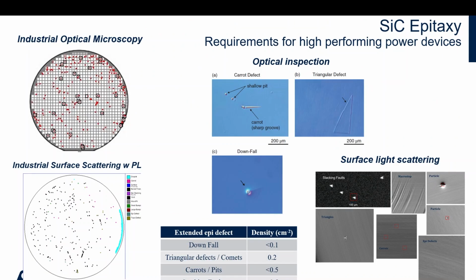And of course, you have to inspect defects. Each defect of silicon carbide after epi that is introduced in the line is measured, typically by optical methods with scattering of the light and also photoluminescence, in order to have a map of each and every defect on the surface of your device. Because this is important for the control of the process, for the control of yield, and the control of reliability at the end of the day.